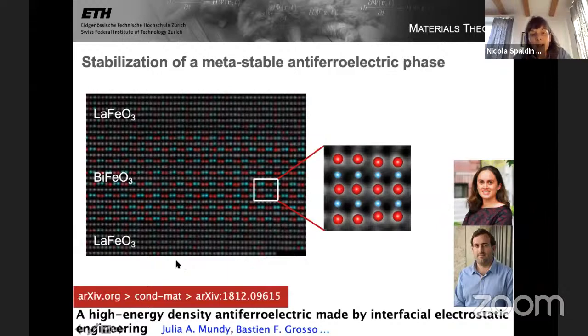And let me show you first the high resolution transmission electron micrograph. This is very beautiful. So this is a heterostructure of lanthanum ferrite, which is a non-ferroelectric insulator. Then bismuth ferrite, the ferroelectric multiferroic material that we've been discussing, and then lanthanum ferrite again. And I'll return to this point later. It's very important that it's lanthanum ferrite here. It's very important that lanthanum is a trivalent ion, just like bismuth. I'll come back to that point later.